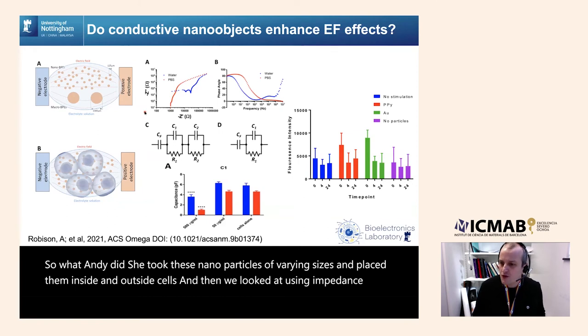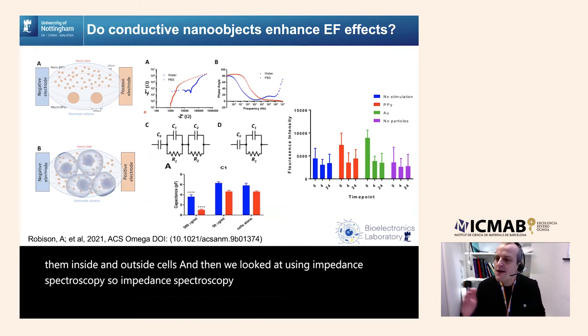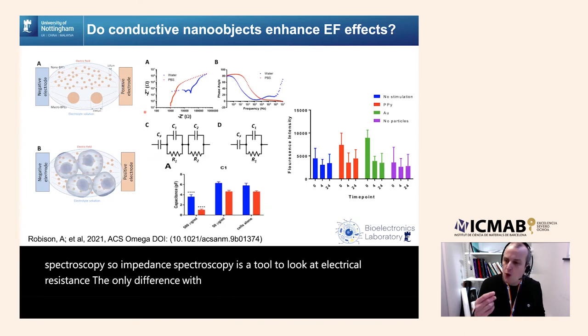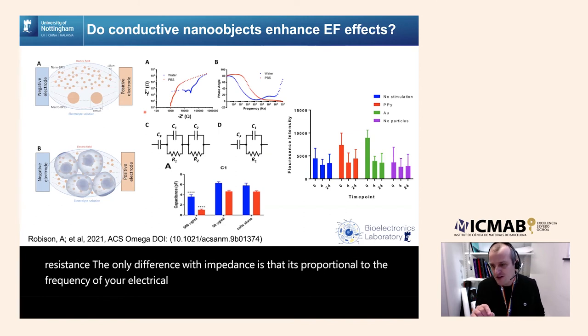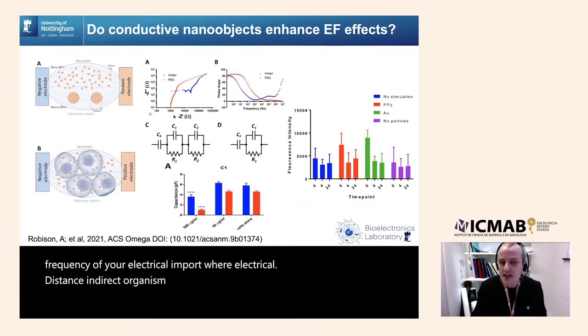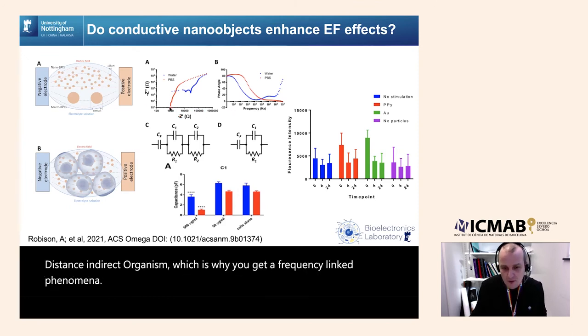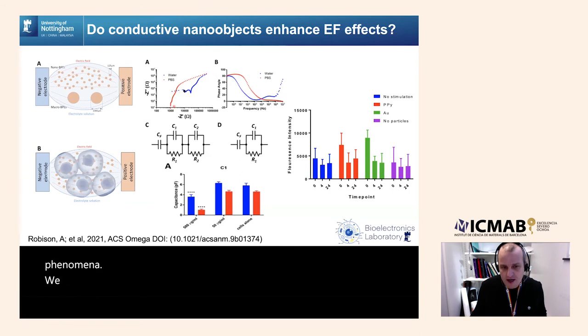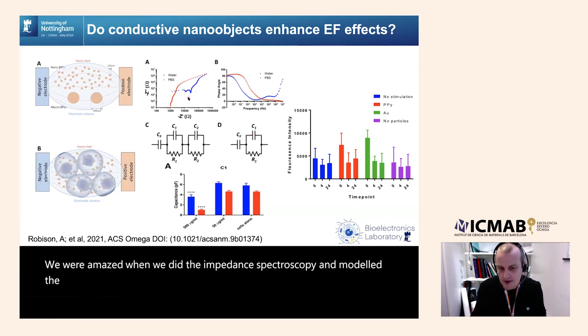So impedance spectroscopy is a tool to look at electrical resistance. The only difference with impedance is that it's proportional to the frequency of your electrical input, where electrical resistance in direct current isn't, which is why you get a frequency linked phenomena. And we were amazed when we did the impedance spectroscopy and modeled the circuits on this impedance spectroscopy results.